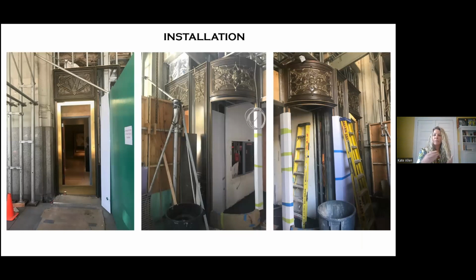And the paint we used is a 1078, a Tnemec Fluoronar. We use it all the time now. It's probably the number one system that we use the most. It's highly regarded, approved by Landmarks. It's got high UV resistance, anti-fading, anti-streaking properties. It has great color and gloss retention. And in this case, because these were aluminum, we used an epoxy primer, but had it been iron, we would have used zinc.